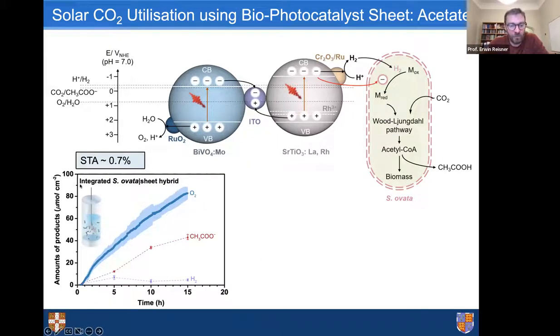So how does this system work? Really quite well if it's integrated. So in this case, we have irradiation time versus amounts of products. We produce oxygen from the oxidation, and then we have the acetate from the bacterial production. And I should point out that this is the expected ratio, 2:1, just the other way around, because oxygen production is again 4 electrons and acetate is 8 electrons.